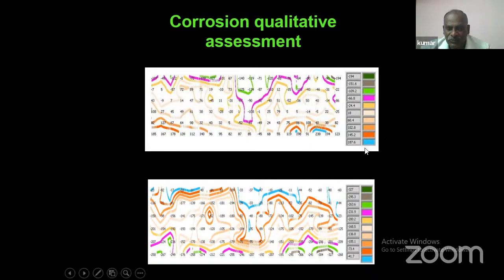For example, the first one: you are seeing where it is more negative, minus 194, it is dark green. So wherever the green is there, in those areas you are getting more corrosion. For example, you are seeing here, on the downside also, it is almost less negative, so this area comes under corrosion. In this way you can compare.